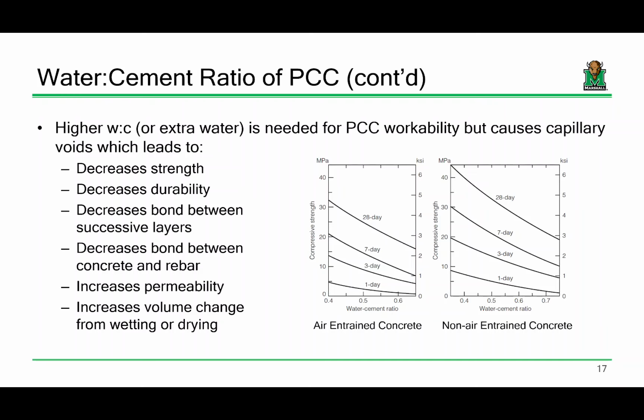It is a common, knee-jerk reaction that whenever you're working with concrete, if the concrete is too stiff and it's difficult to work with, just throw in a little bit of water and that'll make it easier to work with. And yes, it will. I won't knock that. But as you start increasing the water-cement ratio, and it doesn't matter if you're dealing with air-entrained concrete or non-air-entrained concrete, it doesn't matter. It will cause capillary voids between the cement-water reaction. That will decrease the strength of the concrete. That will decrease the durability of the concrete. That will decrease the bond between layers, the bond between concrete and rebar. It ups the permeability. It is like the worst thing that you could do as a mix designer to fix workability by just throwing a little bit of water in there. It'll be okay. No, okay?